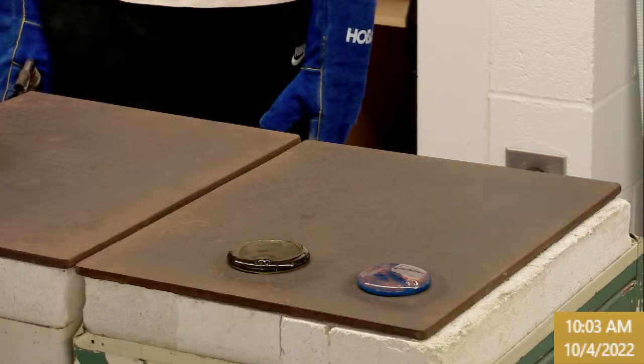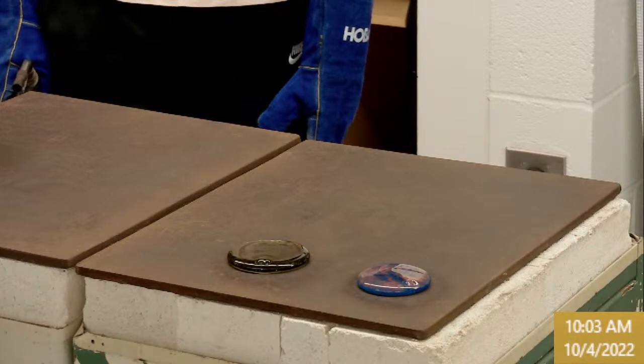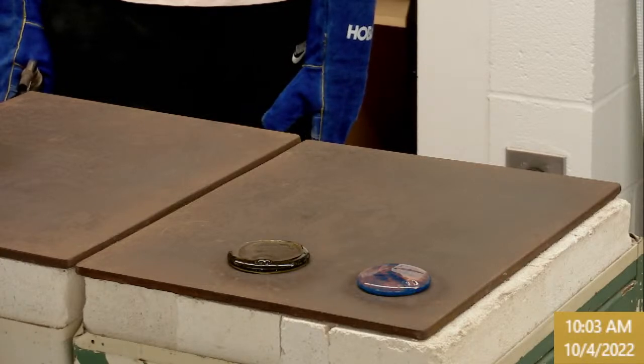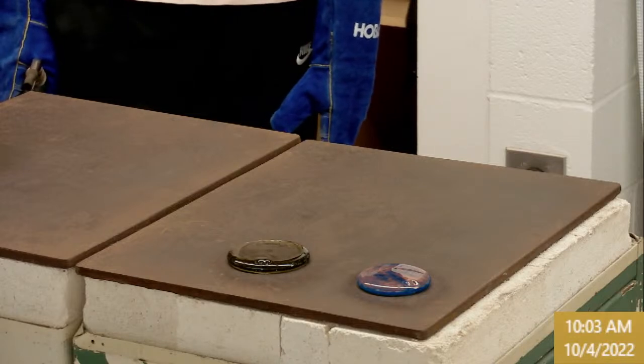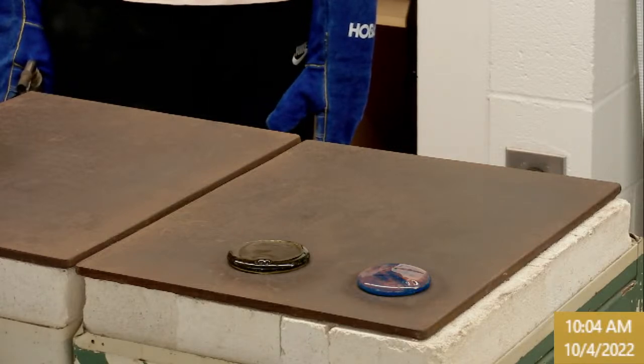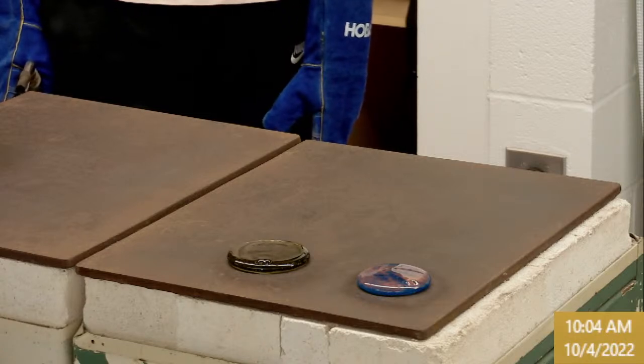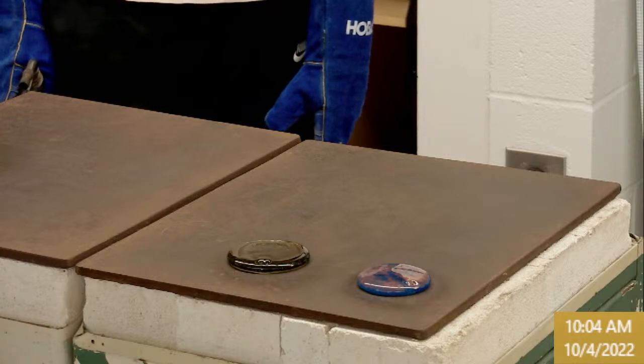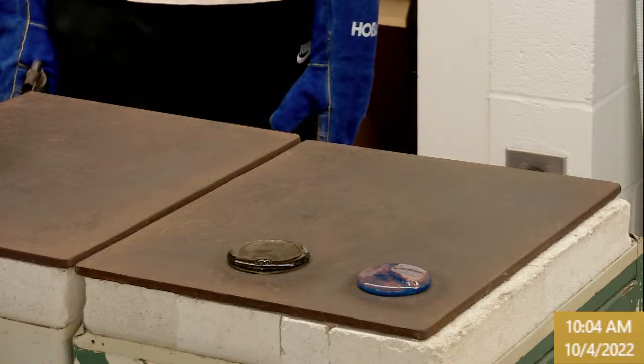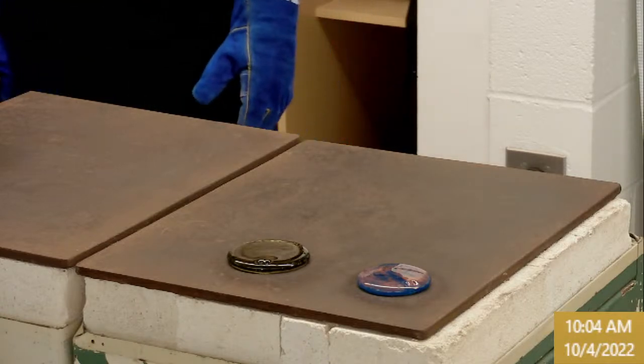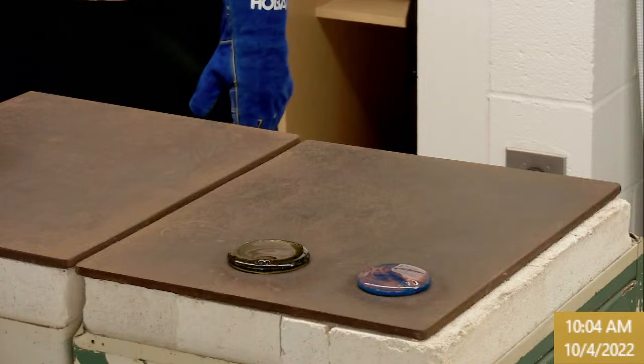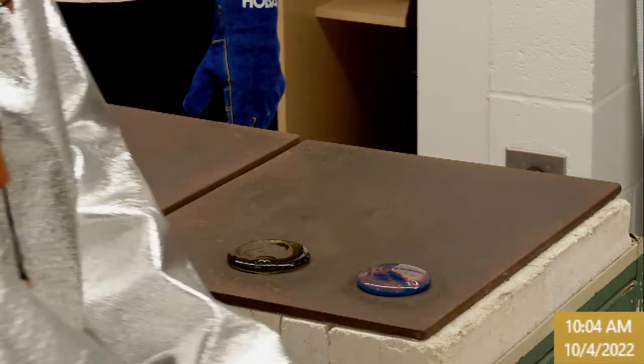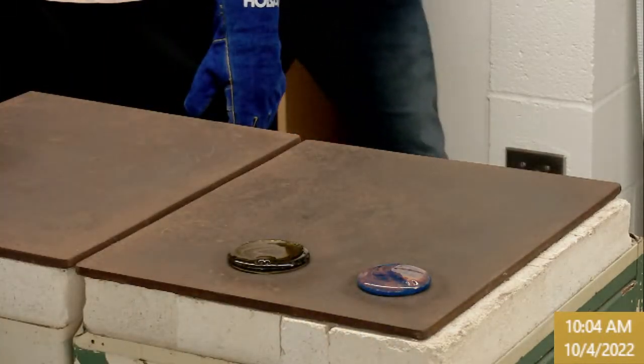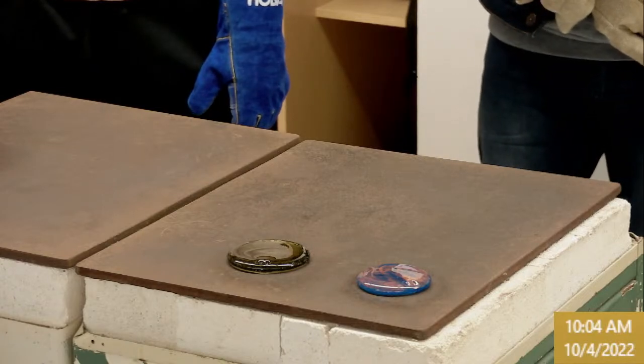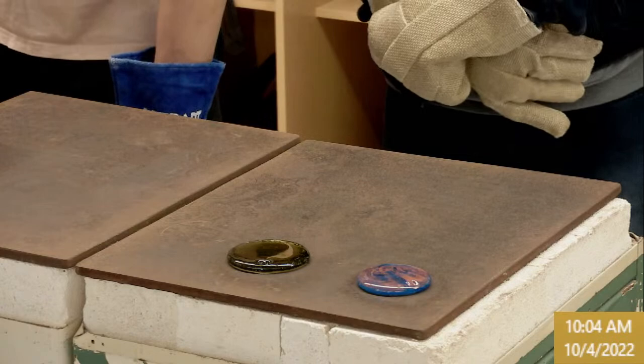You're also hearing what's called crazing. Every time you hear that sound, a new little crack is forming in the glass that's residual on the inside of the crucible. The reason for that is differential shrink rate. So the coefficient of thermal expansion of the ceramic is different than the coefficient of thermal expansion of the glass. And so as that crucible is shrinking and the glass is also shrinking, you'll get these tension fields in the glass, and that is relieved by breaking the glass. And so we will hear eventually a chorus of crazing that'll be occurring there. And for those of you that happen to be up here, feel free to stand up if you want to get a little closer, you can actually see the cracks forming if you know where to look.